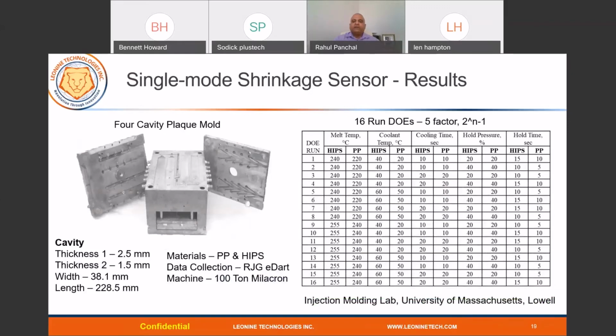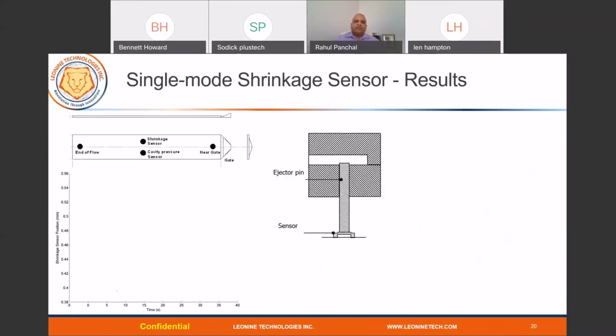So for this design verification and validation, we ran a 16-run DOE with 5 factors, with a plaque mold having 2 different thicknesses, where we used 1.5 millimeter and 2.5 millimeter thickness with polypropylene and HIPS. So one is a semi-crystalline and one is an amorphous material. We used the injection molding lab at the University of Lowell, and I was still a student there. So these are the results.